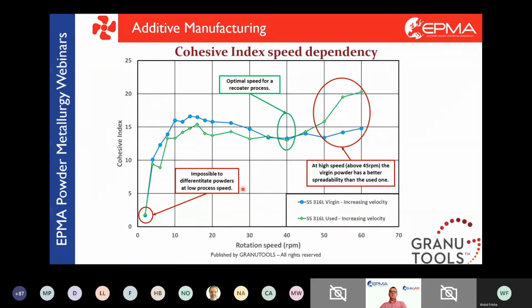What we notice is that the cohesive index depends on the speed, and at low speed the used powder has a better cohesive index than the new powder. This is because when you put a powder inside the machine, there is some filtering, so we lose the fines, and with less fines there's less contact ratio, so the cohesive index improves. But at high speed there are other effects, like the carbon content in the powder being a bit different, so the cohesive index is not the same.